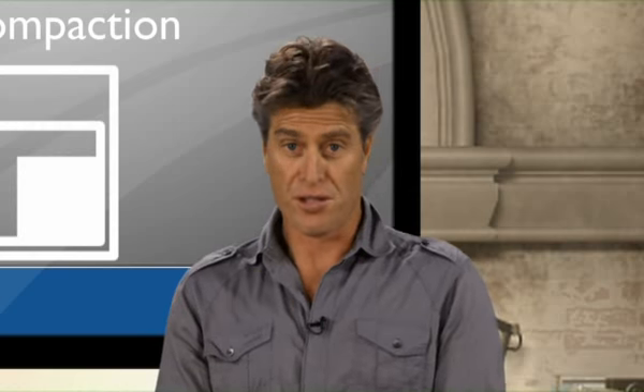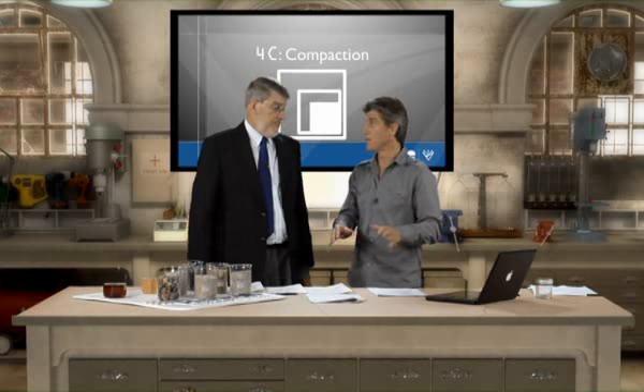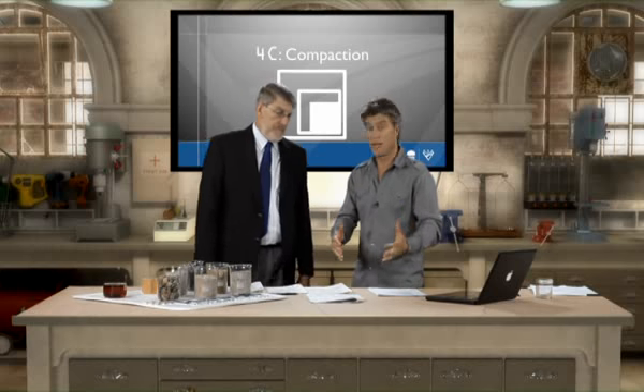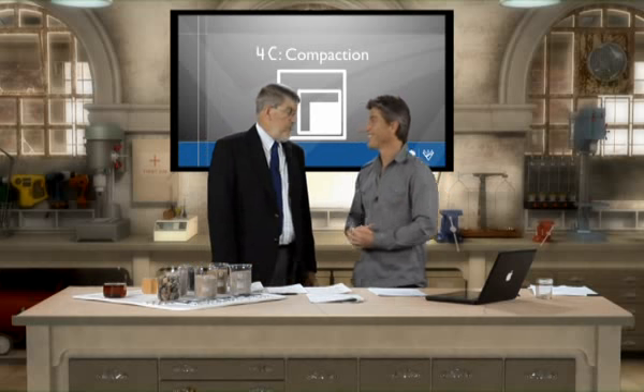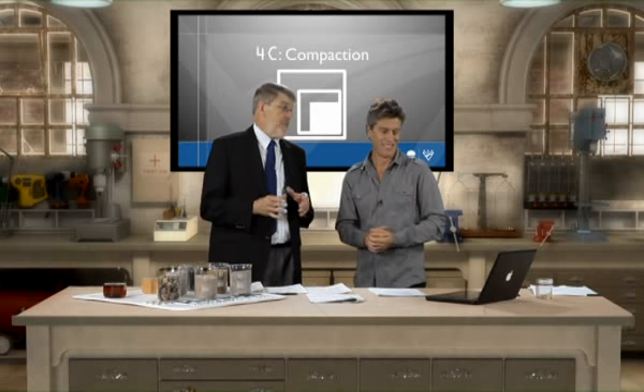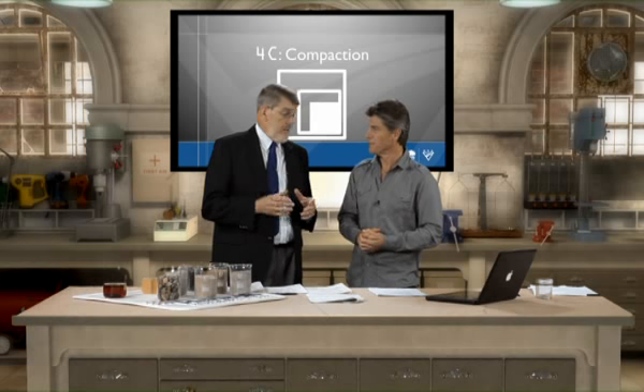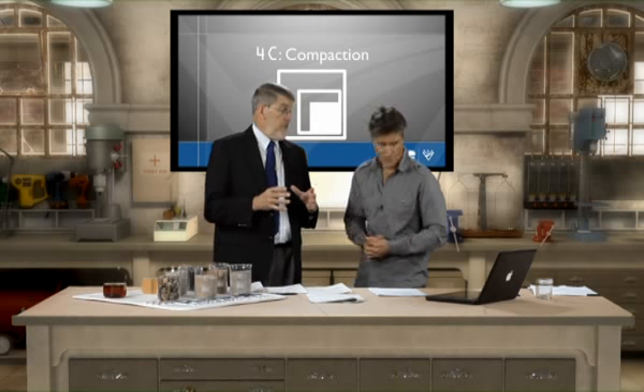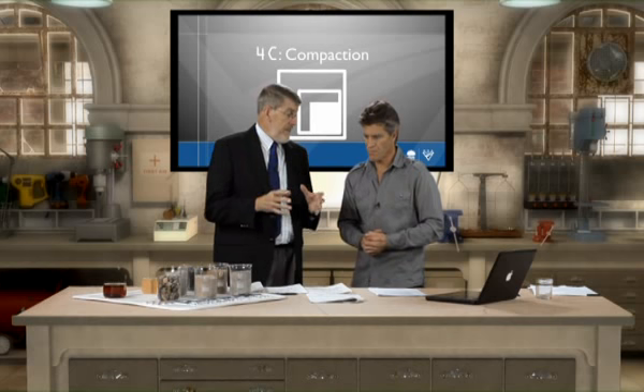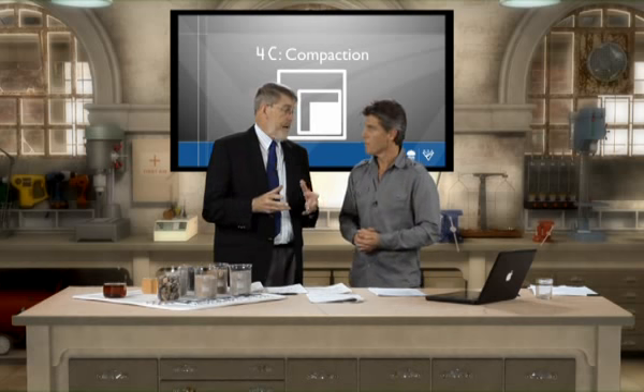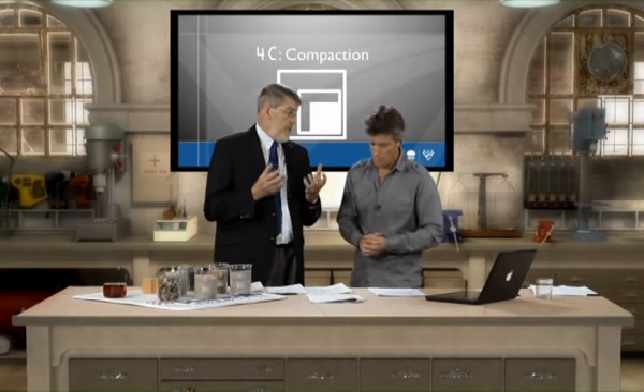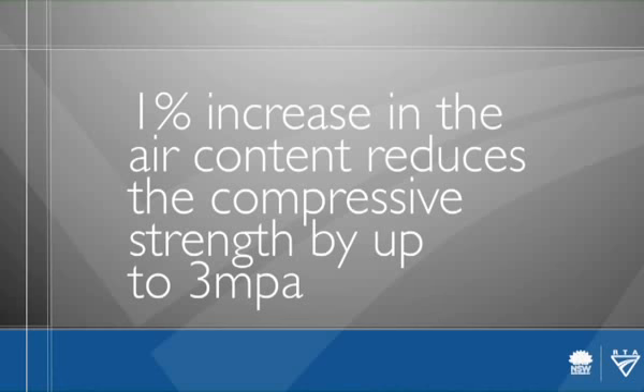So on to the fourth C, which is all about compaction, and my understanding is the concrete mixes in, we've started to get the vibration happening, but I'm sure there's more to it. There certainly is, Peter. In fact, you could say compaction is a very important part of the process, because what we're doing is placing concrete from the truck that's got air in it, and what we're trying to do with the compaction is to get that air out of the concrete. And in fact, a 1% increase in air content reduces the compressive strength by up to about 3 MPa. Makes a difference, so it is significant.